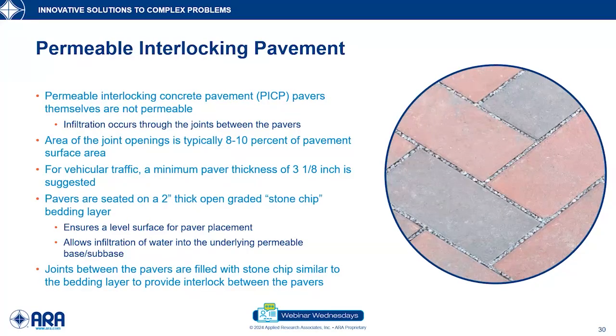The only difference between permeable interlocking concrete pavers and conventional ones is that we do not put sand in the joints. Instead, we put stone chips — typically something like 3/8 inch diameter — in the joints. The pavers are seated on a bedding layer to allow a nice smooth surface when driving across them. The stone-chip joints provide interlock but reduce the structural capacity of permeable interlocking concrete pavements compared to conventional pavements. Bases and sub-bases use open graded aggregates. We've been using open graded drainage layers for concrete and airport pavements for many years, but here the whole pavement needs to be permeable.